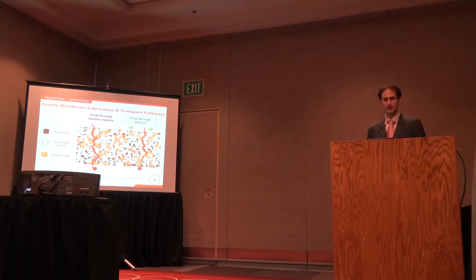And so these defects are transported through the membrane by the spaces which surround our zeolite crystals, as well as those regions which aren't occupied by zeolite crystals. And so with this understanding about zeolite membranes, we see that there's two different transport pathways. And so thereby, conducting a few tests using a small number of gases, we're able to describe these defects. And then in describing those defect pathways as well as the zeolite crystal pathways, we can better design our membranes, and we can also evaluate them.